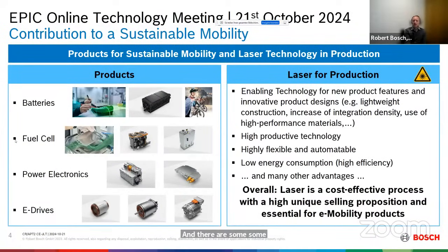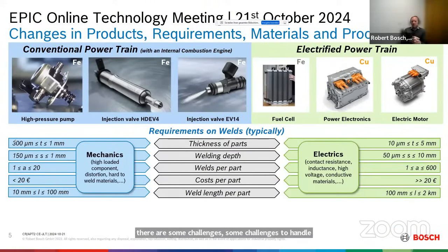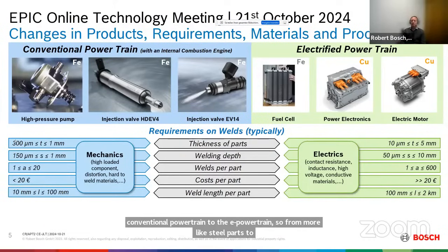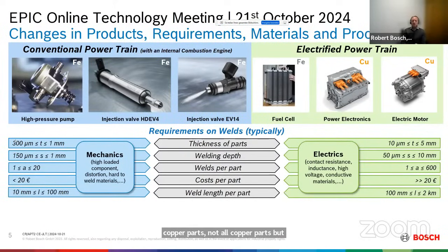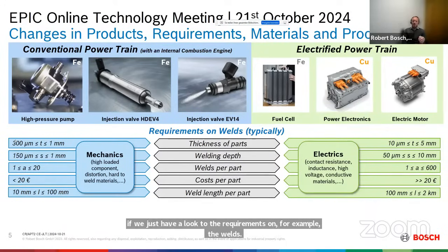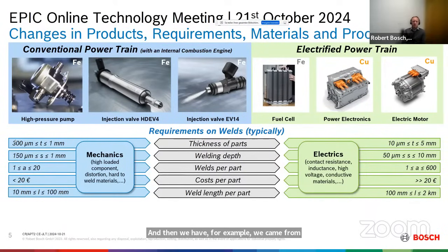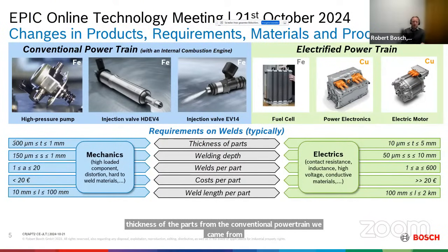challenges to handle. And this challenge can be easily explained by a few simple calculations, for which I want to take you on small deep dives. If we take a look at the changeover from the conventional powertrain to the e-powertrain, so from steel parts to copper parts, not all, but in most cases. And if we look at the requirements on, for example, the welds, we came from part thicknesses of 300 microns to roughly about 1 millimeter in thickness.